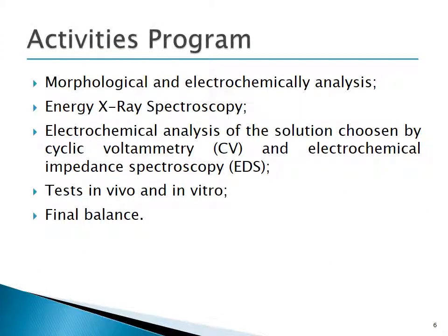The activities program. We will need to test and evaluate different silicon probes, both morphologically and electrochemically. The silicon probes have different structures and different electrode diameters, and so we need to test them all. Next, using energy dispersive X-ray spectroscopy, the characterization of the coating solutions is performed. After the solution is applied to the electrode, using a potentiostat, we proceed to the electrochemical analysis by cyclic voltammetry and electrochemical impedance spectroscopy. And then we test the electrodes in vivo and in vitro using anesthetized rats.